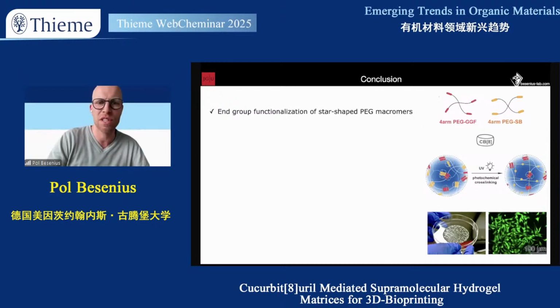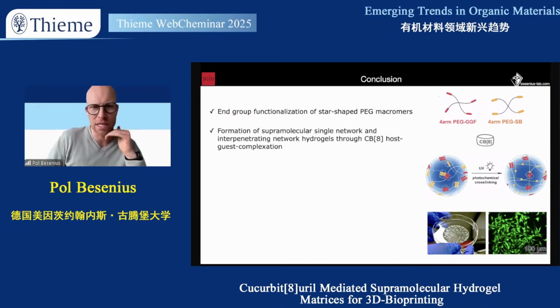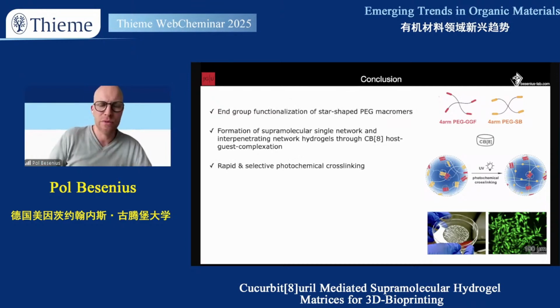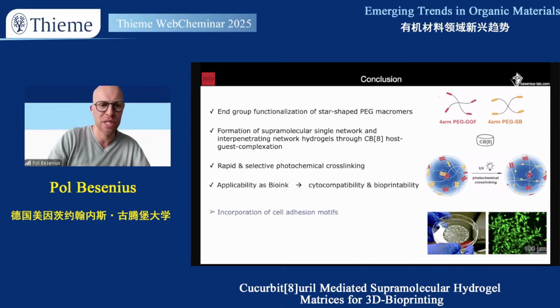Organic chemistry, very simple functionalization of star-shaped polyethylene glycol macromers or macromonomers, which are then connected via CB8-mediated host-guest chemistry to form 3D networks, and through photochemical cross-linking of a small fraction of these supramolecular units, you can play around with the stability, as well as the dynamic characteristics of the network, and they can be applied, and apparently they seem to be very cytocompatible and bioprintable.